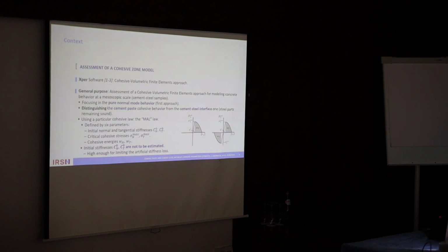I will use a particular cohesive law which is called MAL law, and which is implemented in the XPER software. This cohesive law uses 6 parameters: 2 initial normal and tangential stiffnesses, 2 critical cohesive stresses, and 2 cohesive energies, so for both normal and tangential opening mode. The initial stiffnesses are not to be estimated as they are not physical parameters, but only numerical ones which are used for calibrating the cohesive model. So to summarize, I focus on the pure normal mode, and the initial stiffnesses are not to be estimated. So at final, only 2 parameters will be of interest in this presentation: the normal mode critical cohesive stress and the normal mode cohesive energy.